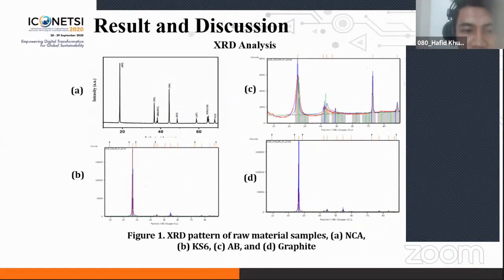Results and discussion. Figure 1 displays the XRD pattern of the starting materials. Figure 1A shows the XRD spectra of the NCA starting material, which corresponds well to a layered structure of alpha sodium ferric oxide. Based on the result of the XRD analysis, the KS6 raw material used is compatible with graphite crystal, with a very dominant peak at a 2 theta diffraction angle of 27 degrees.